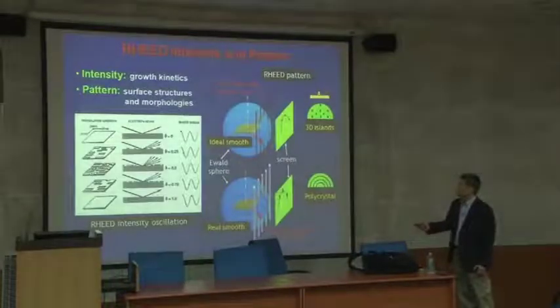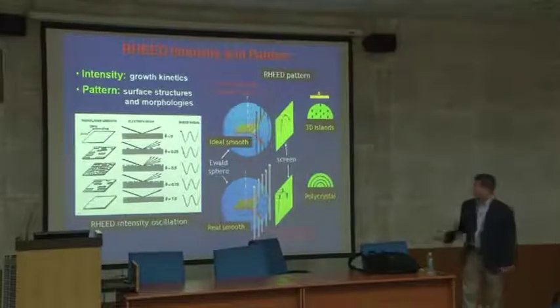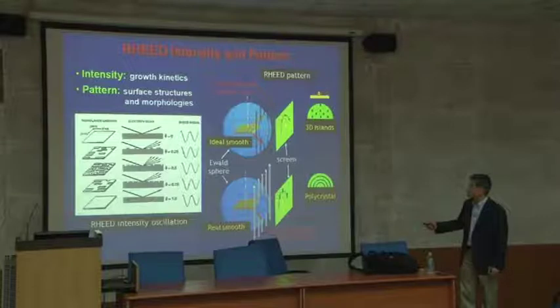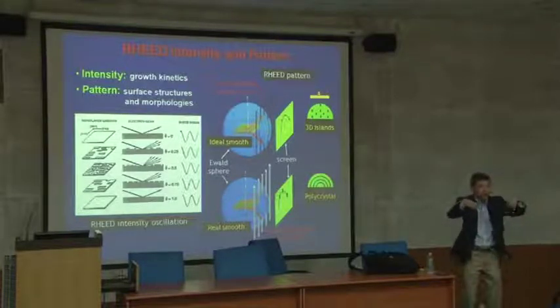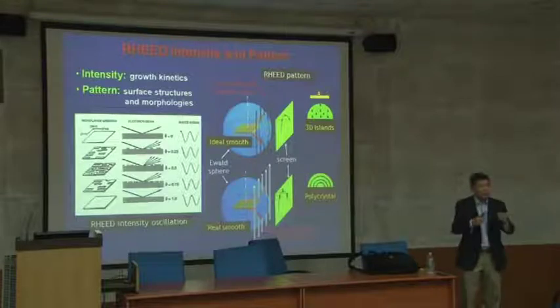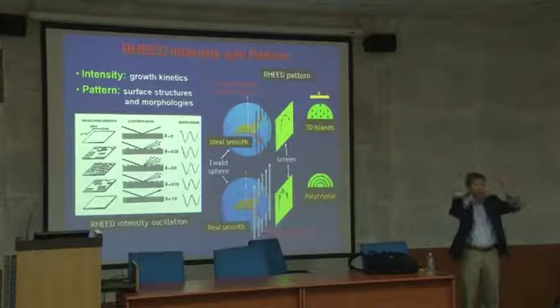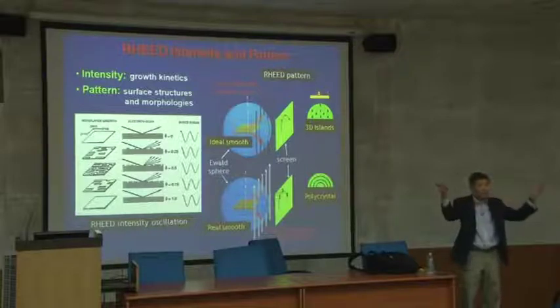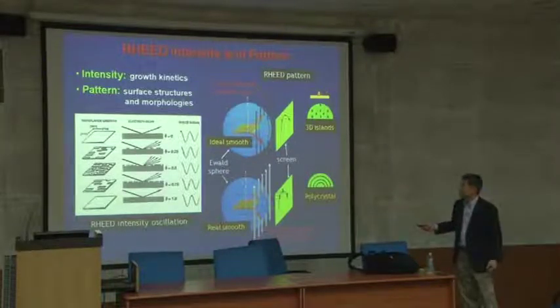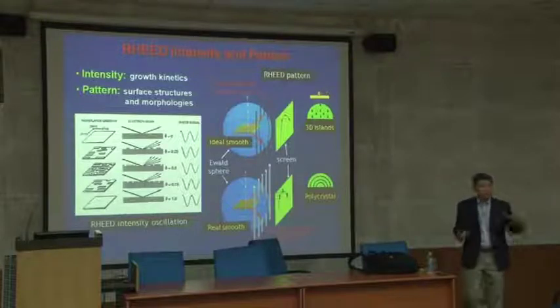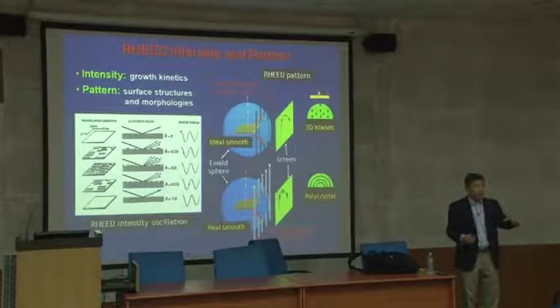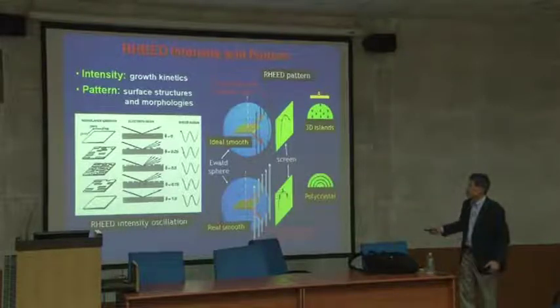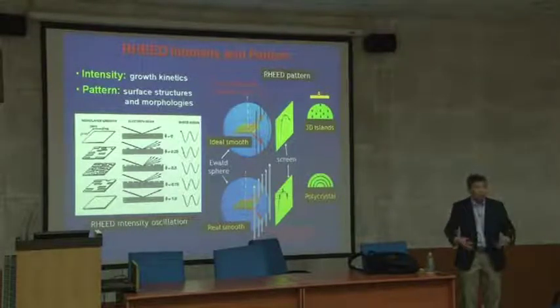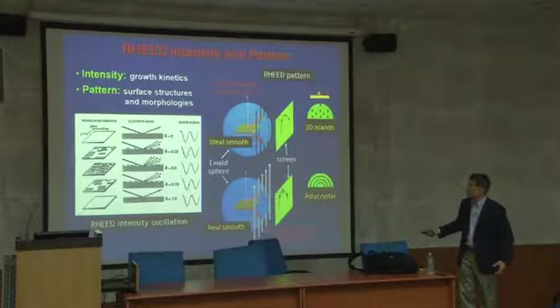Then you will see its intensity of reflection is very, very bright. Okay? And this bright beam here initially, and when your atoms arrive on the surface, same way, like a water droplet on the mirror, the reflection scatters everywhere, and the intensity goes down. And this intensity goes down when you have roughly 50% coverage. At 50% coverage, you go down to the minimum. Then when you go to full coverage, you go back up again.